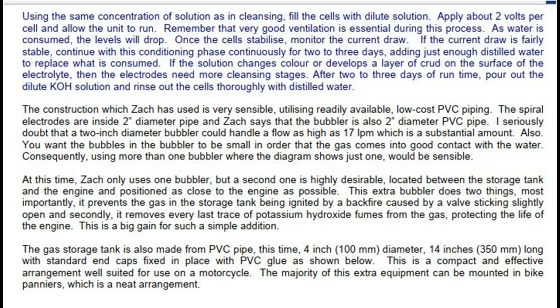If the solution changes color or develops a layer of crud on the surface of the electrolyte, then the electrodes need more cleansing stages. After 2 to 3 days of runtime, pour out the dilute potassium hydroxide solution and rinse out the cells thoroughly with distilled water.